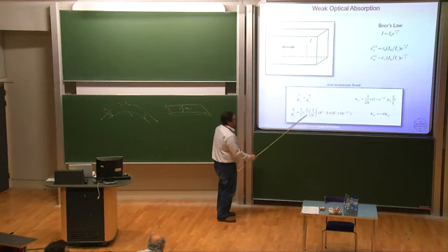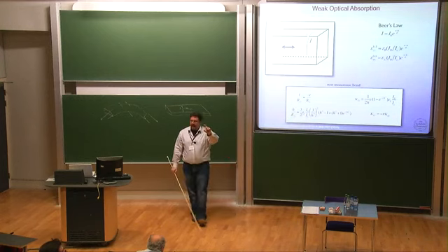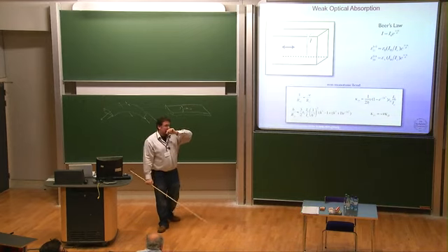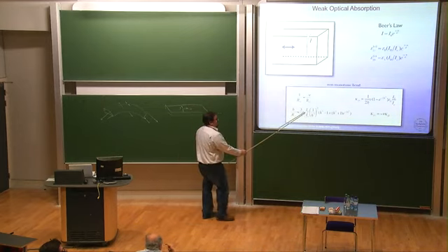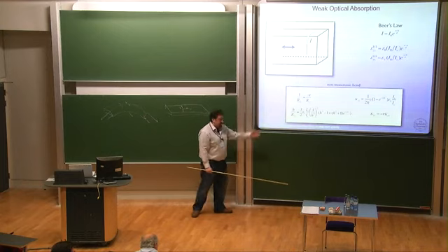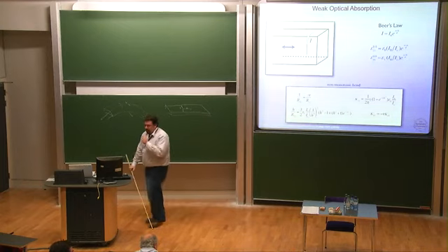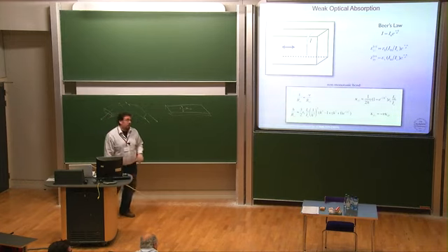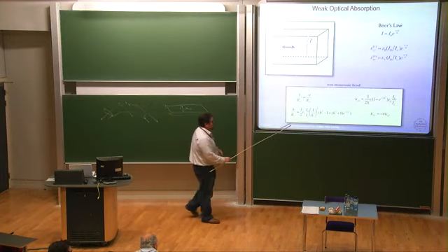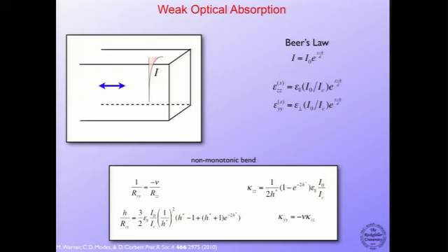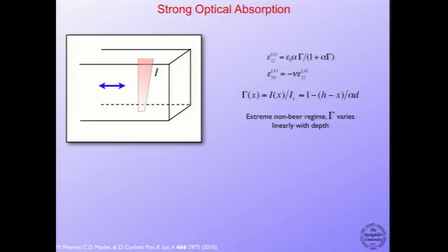So you get this kind of curious sweet spot in the thickness relative to the penetration depth. In terms of the rescaled H, that sweet spot happens to be at 1/3. If you want maximal bending in this kind of system, then you want the thickness to be 1/3 of the penetration depth. And you just optimize the polynomial part of the equation to get that. Okay, what about strong optical absorption? Right, so this was the weak absorption. I think this is something that Mark is going to talk about.